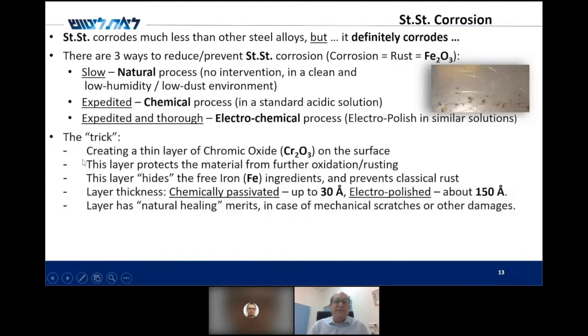The trick is creating a thin layer of chromic oxide, Cr2O3, on the surface. This layer protects the material from further oxidation and rusting. It actually hides the iron from the free air and prevents the classical rust, which is the Fe2O3. And it's a very, very thin layer. The thickness of it is up to 30 angstrom when it is chemically passivated, and up to 150 angstrom when it is electro-polished. Roughly, this is the number of single atom layers, because an atom is in the order of magnitude of between 0.8 to 2 angstrom. So this is roughly 30 atoms, and this is roughly 150 atoms.